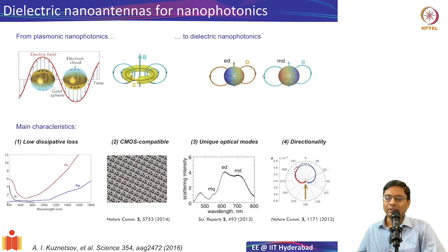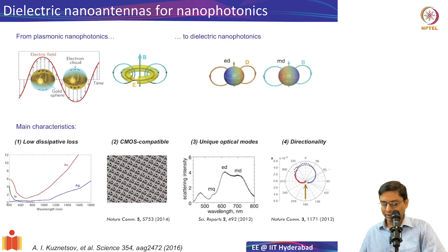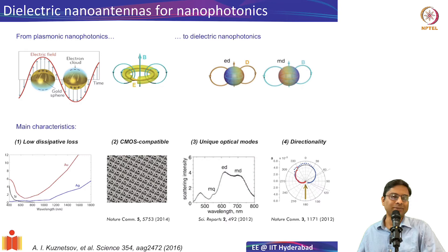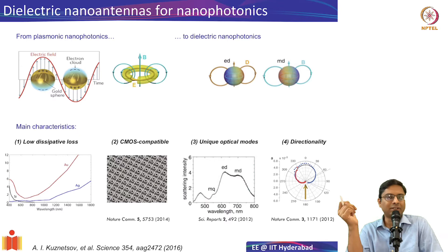Traditional plasmonic resonances — including split-ring-type structures with circulating electric fields causing a magnetic field — suffer from loss. A plot shows loss for gold and silver versus wavelength; silicon's loss is quite low. Amorphous silicon has an optical band gap of about 700 nm, so above that wavelength it is essentially lossless. This is one key reason people have moved toward dielectric nanophotonics, starting roughly around 2015.